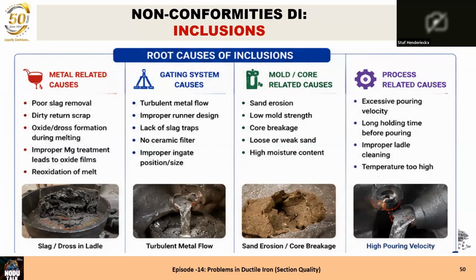If you don't have that, you are asking for problems, because your first metal is dirty, it is in contact with the cold mold, and it will be cold and dirty, and if this metal goes in the casting, you have inclusions for sure. So make sure that you have a slag trap under the sprue and at the end of the runner. No ceramic filter. A filter can, let's say, hold everything in front of the filter, not after the filter. Everything that happens after the filter, it will not hold. And the second thing is, a filter, in my experience, does not hold dross, because dross is such a fine composition with a high fluidity, and it goes through the filter.